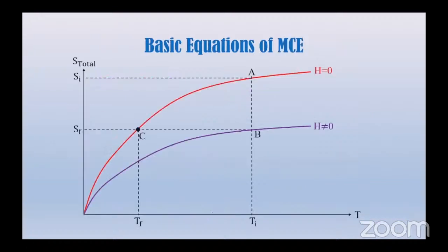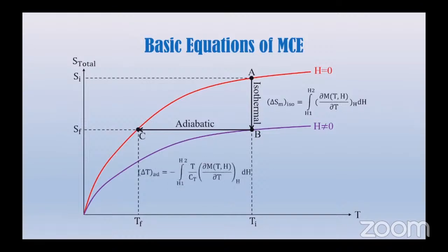Basic equation of the magnetocaloric effect. The basic equation for calculating the magnetocaloric effect is a contribution from two main processes, isothermal and adiabatic. For the isothermal case, we simulated the integration of the derivative of magnetization, and for the adiabatic case, we simulated the above integration multiplied by temperature divided by total heat capacity. This has been done through very powerful mathematical software.